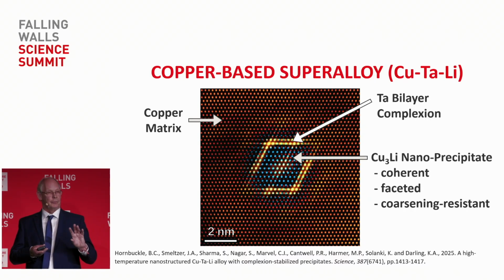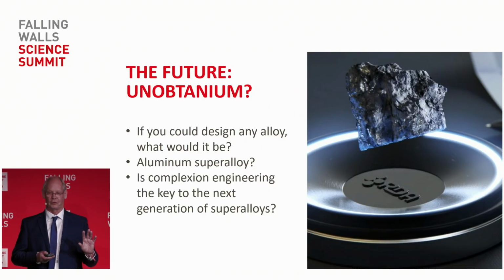And the real benefit of this material is the stability of it. The Achilles heel of nanostructured materials is that they're not stable. This material we heated for 10,000 hours, which is over a year, at 800 C, which is close to the melting point, and the strength dropped by just 4%, still at 1,000 megapascals, and the grains grew only 1 atom spacing every 100 hours. So it's incredibly stabilized. So we're very happy with the results of that superalloy.